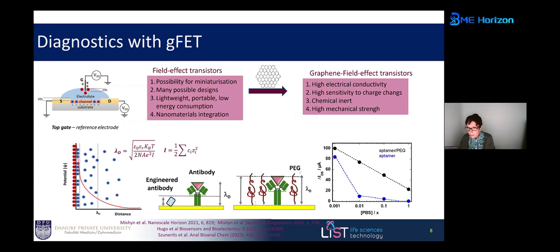And here you see an example. You can increase this Debye screening length by using, for example, polyethylene glycol molecules on the surface. And this is validated by some of the experiments I show you here. If we look at the drain source current of a field effect transistor, if we only have the aptamer present, we see that around 0.01 ppb you almost lose your signal. However, if we have a mixture of aptamer and PEG units, we definitely have a decrease in sensitivity in high ionic strength solution, but we are still able to measure at really high PBS concentration.